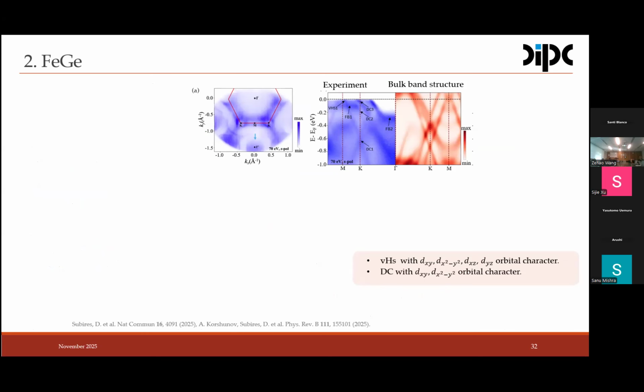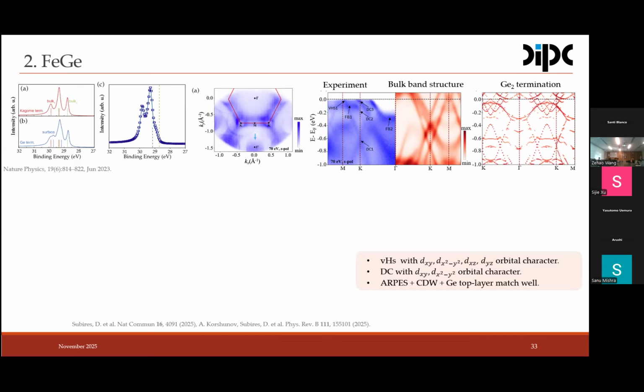But then, if we compare the bulk band structure obtained for the low temperature phase with what we actually resolve in the experiment, we can see some bands which actually match, for instance, these bands here, which cross at the K point, correspond to these ones, the Dirac crossing. Then there is this band at gamma, which is this one, right? The other bands, which we cannot match, actually come from the germanium 2 termination, the honeycomb termination. So we mix the bulk band structure plus the surface bands from the DFT and compare with the experiment, we can actually match this flat band here with the surface band in the germanium 2 termination. So we put all together.